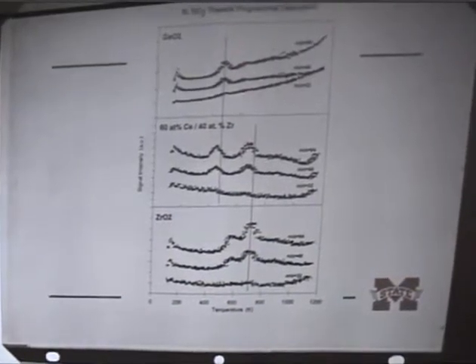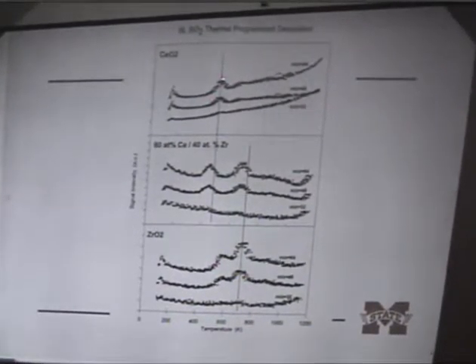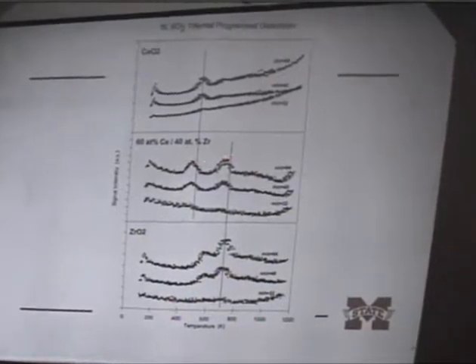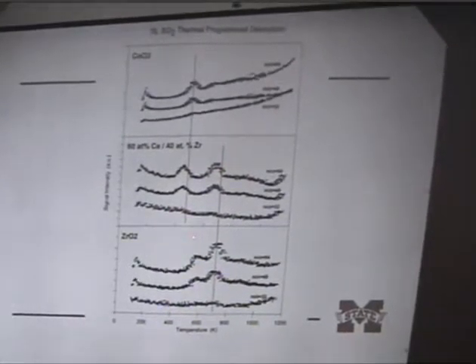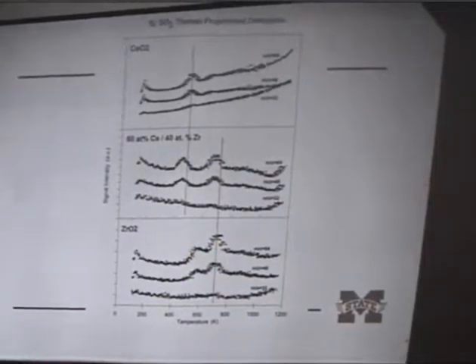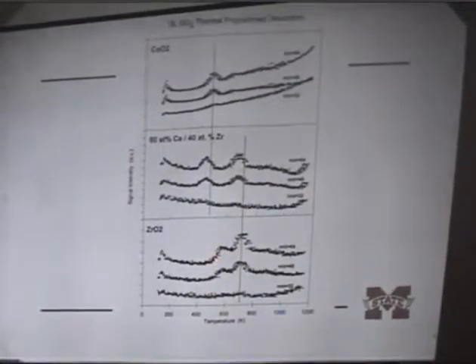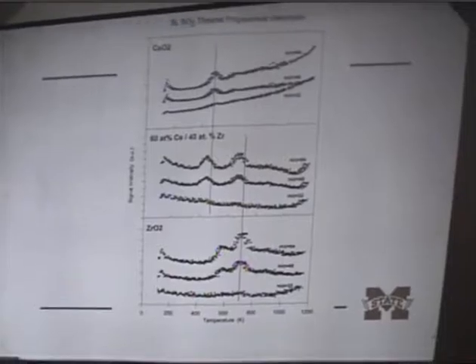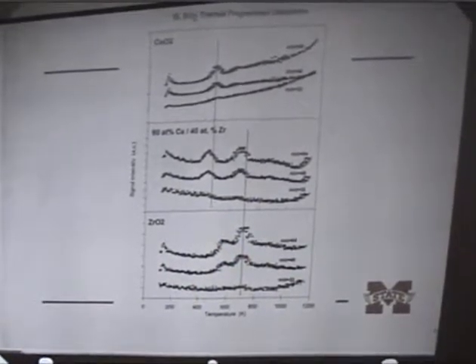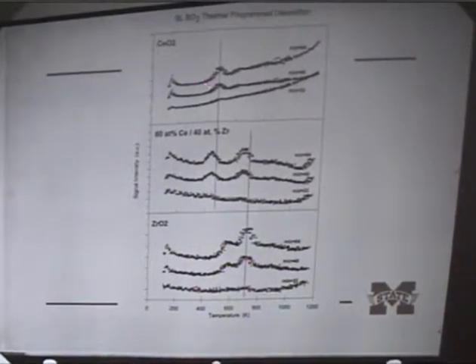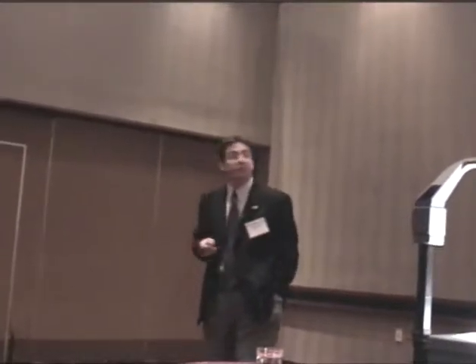Now what we do see is one chemisorbed desorption state for ceria. We see two chemisorbed desorption states for the mixed oxide, and then for zirconia we see one primary one, and you can call this a second one or a shoulder that's over here on this particular side. So TPD gives you a little bit of a hint about things. This tells us we think that we're seeing a single type of desorption state for SO2 on ceria, two different ones for SO2 on the mixed oxides, and then one with some sort of energetic difference on the zirconia, and we'll come back to this later.